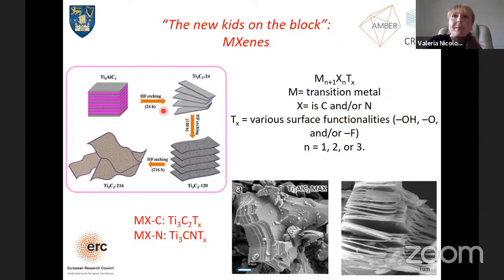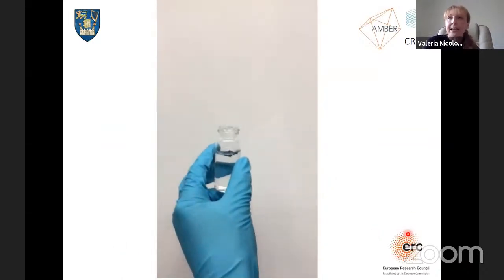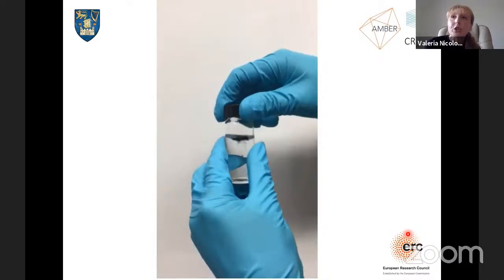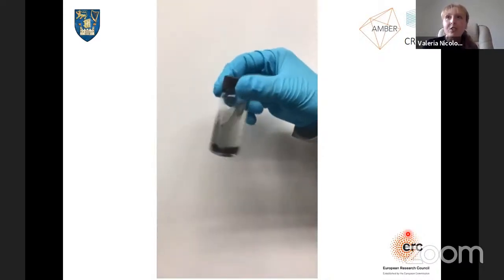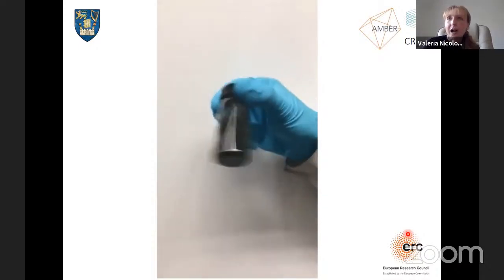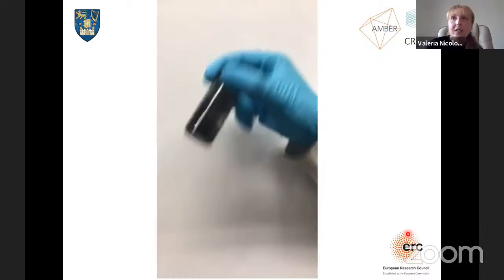So what we do here is some HF etching of these layers, and we go from a crystal of this type, the MAX phase, to an accordion type of expanded structure where we have etched away the middle bonds basically. These are made of titanium carbides, with all different sorts of stoichiometries. Once you reach these accordions, exfoliating them is extremely easy. All you need to do is put the material in water and give a simple handshake, no sonochemistry, no shear mixing, nothing of that type. And all you get is a very nice and stable ink.